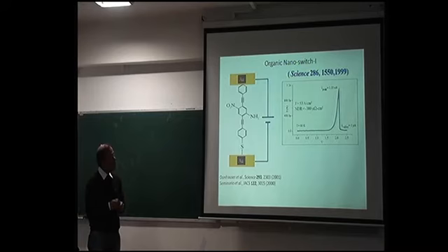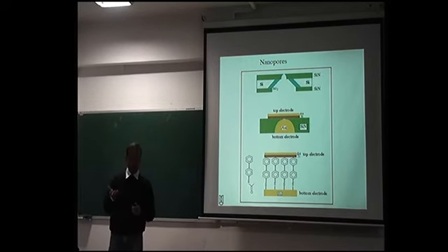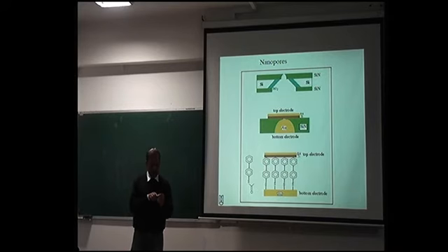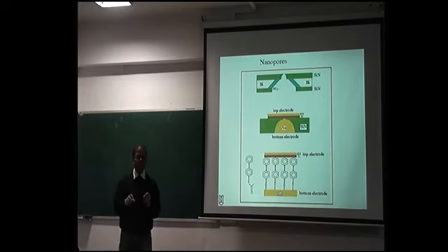is a little doubtful because when you make the second layer, a gold filament can easily form between the top electrode and the bottom electrode. Okay. And there is electromigration, which was shown long before, that this metal filament can act as an on-off switch, and this is reproducible. And that's why you have seen thousands of papers recently on resistive memory based on oxides. They are based on this metal filament: you apply a bias, a certain threshold bias, and the filament breaks. When you remove the bias, they rejoin and you get back your on and off current.